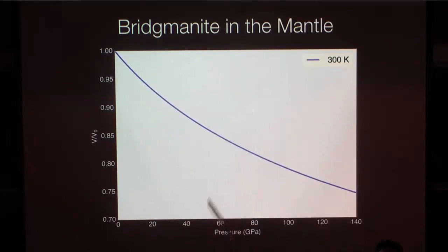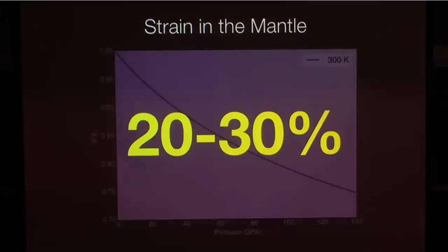And when you increase pressure, obviously volume decreases, but you realize that it doesn't decrease linearly. It has a curvature that actually tells you something about how the compressibility changes with pressure as well, right? So the compressibility decreases, I should say, with pressure. So as you go to higher and higher pressure, material becomes stiffer and stiffer, and that explains why you have this curvature, okay? So you cannot use that linear relationship anymore.